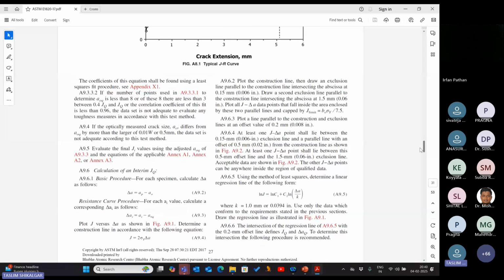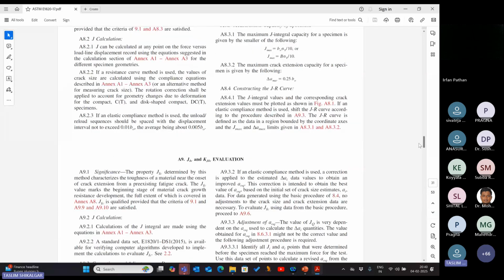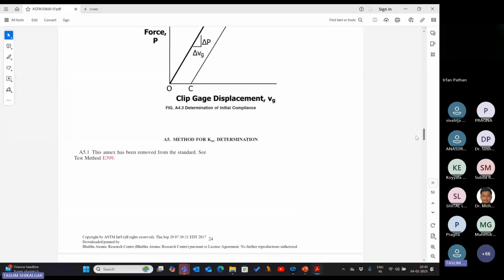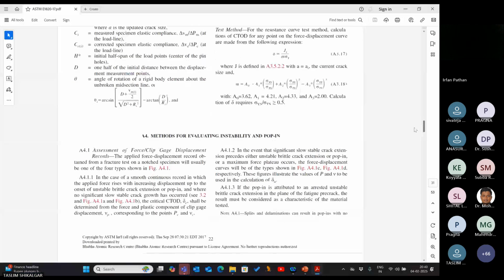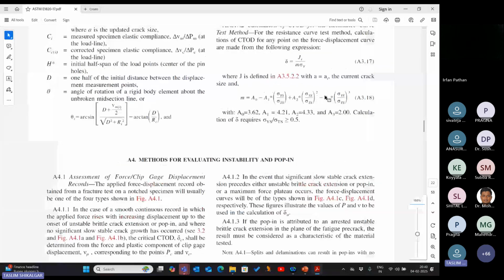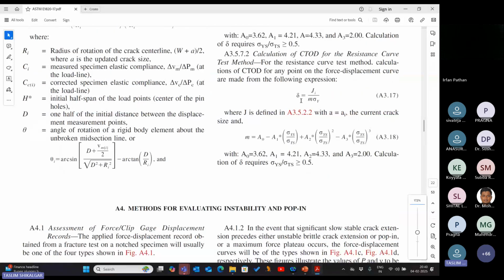There is one similar correlation available. Here you can see this. I proposed a similar correlation, like J, and this is the CTOD. This is the plastic constraint factor, which is a function of sigma ys divided by sigma uts, and four constants A0, A1, A2, A3. This is a polynomial equation.